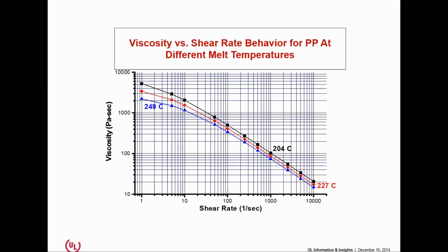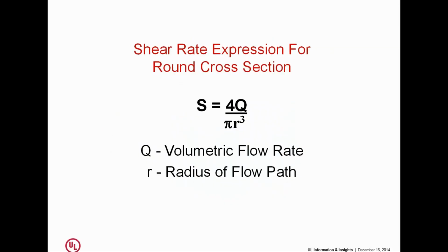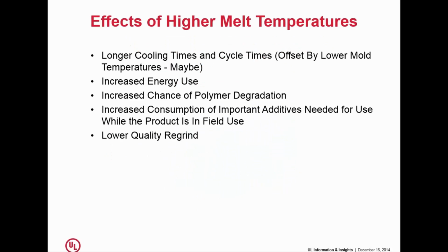And so there's a point at which we reach a point of diminishing returns, and the flow path becomes too small, and the pressure drop goes up faster than the shear rate goes up, and that's where you start to reach your balance point. If you're doing flow simulation, these 2 equations I just showed you, these are the 2 equations you're supposed to be balancing, because every process has an ideal balance between shear and temperature. And if you do your process development right, you find that balance point and you stick with it for the rest of the life of the product. If you don't, then you're kind of guessing a lot of the time.